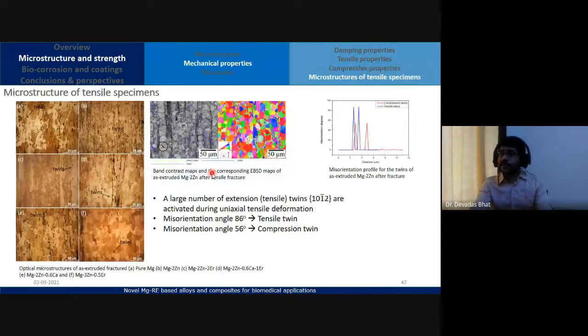We could also see some twins for our samples. Okay, extension twins, that's the tensile twins were formed, and in some studies we also saw that by activating such tensile twins, it can reduce the corrosion rate of the alpha magnesium matrix, and it will weaken the corrosion anisotropy between the two differently oriented grains. Okay, why? How does it work?